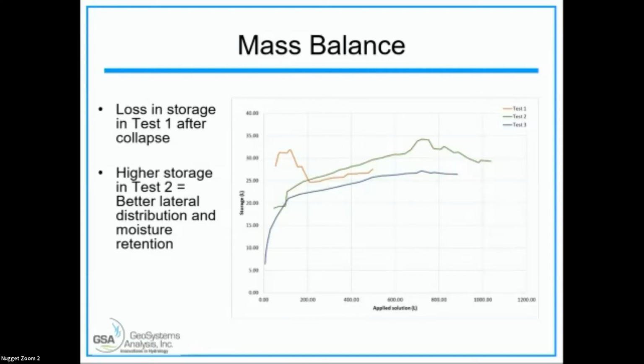And then if you just look at the mass balance, which we were tracking by what we're putting in, what was coming out and accounting for evaporation, what we see is that with test number 1, there was a big jump. And this is storage, by the way, in terms of total liters within the column. We see a big jump in test number 1, and then it drops off, and then it slowly starts to come up. And that's consistent with the water content sensor data. With test number 2, the slow ramp up, we see much more accumulation of storage and higher storage than in test number 3, which is the fast ramp up.